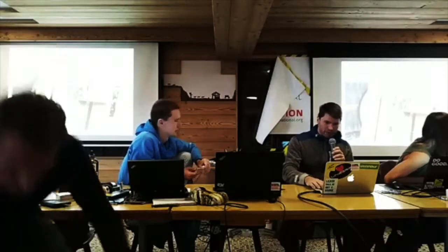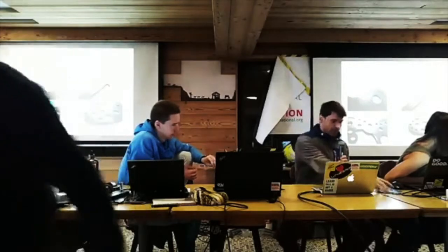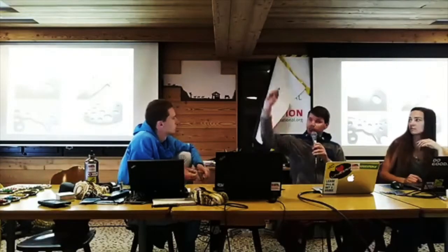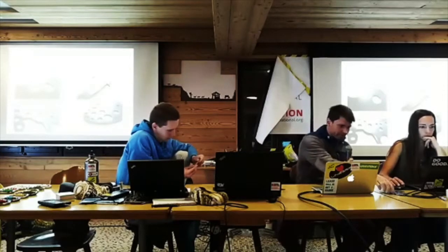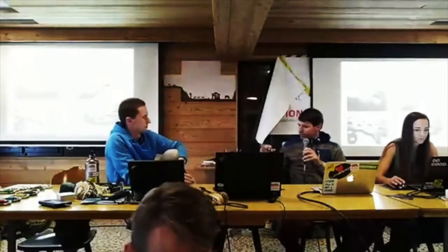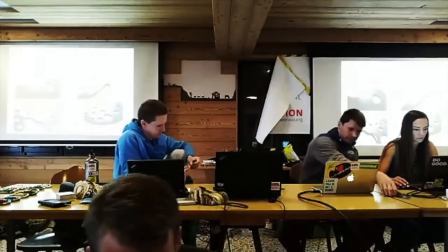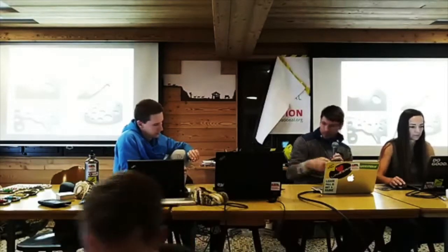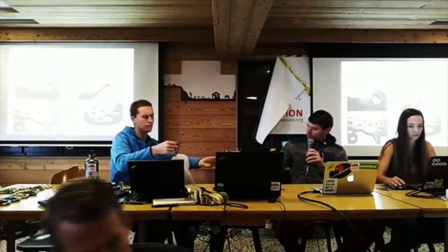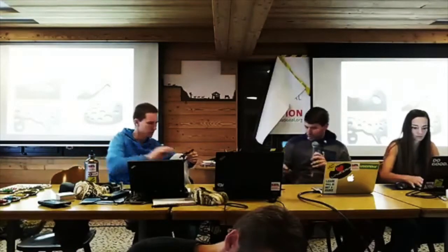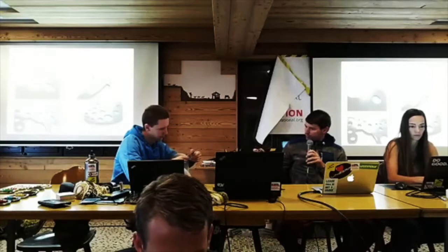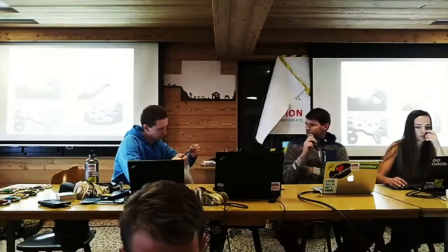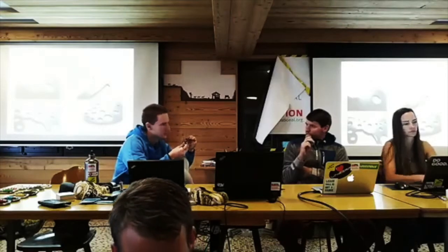Okay, so we tested all 4 kinds of materials. These are the results. We have this aluminium piece. It's this little piece over here. And I'll pass it around and you see a really deep and sharp notch in it. Pass it around so everyone can see it. Then we have this stainless steel, same result. We have some usual, mild steel, and we have some high strength steel, which doesn't see any surface damage from this test.